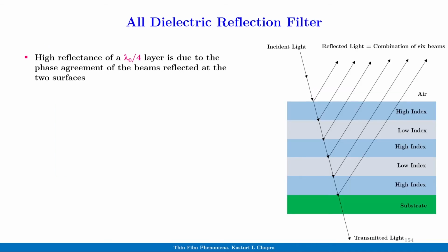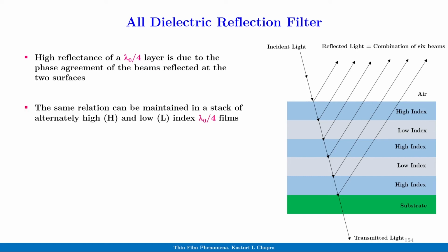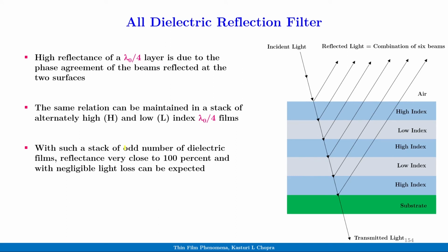We will now discuss the theory of the all dielectric reflection filter, which can be used as a band pass filter. We already have seen that the high reflectance of a lambda 0 by 4 layer is due to the phase agreement of the beams reflected at the two surfaces. The same relation can be maintained in a stack of alternately high and low index lambda 0 by 4 films. With such a stack of an odd number of dielectric films, reflectance very close to 100% and negligible light loss can be expected.